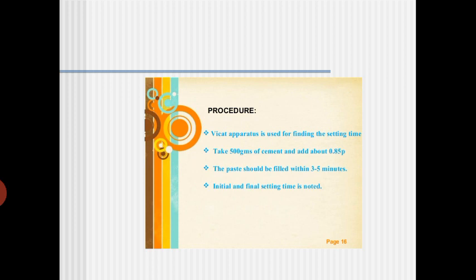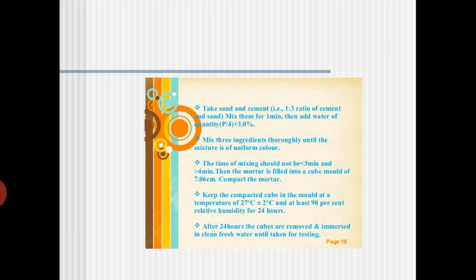Procedure: the Vicat apparatus is used for finding the setting time. Take 500 grams of cement and add about 0.85 times the water for the paste, and the paste should be filled within 3 to 5 minutes. Within 3 to 5 minutes you have to fill it, and the initial and final setting times are noted. Make sure the initial time is not less than 30 minutes and the final time is not more than 10 hours.